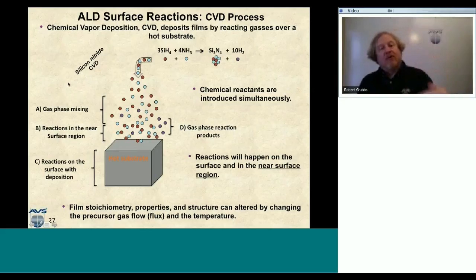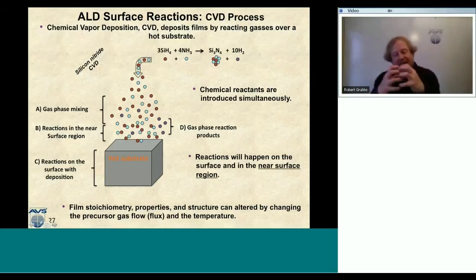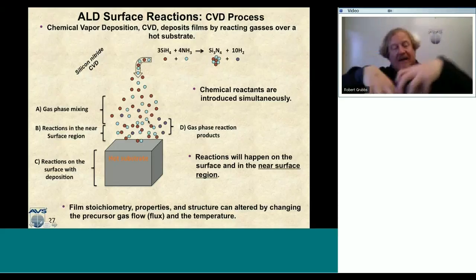So if we broke the CVD process down, we would have this region A where we have this nice mixing of gases, and then we have this region B. And this region B is very important to point out, because we get these reactions in the near surface region. The substrate is hot. It has enough energy to make some of these gas phase molecules react with one another, and as they react, they come down onto the surface and probably react even more on the substrate. Or you can have some of these individual molecular gases adsorb on the surface and then react.